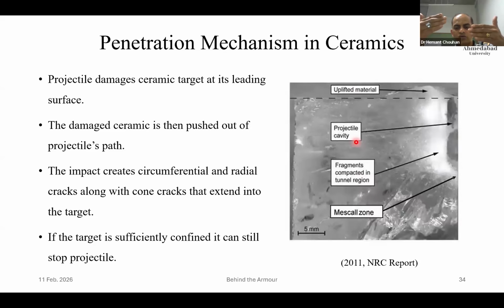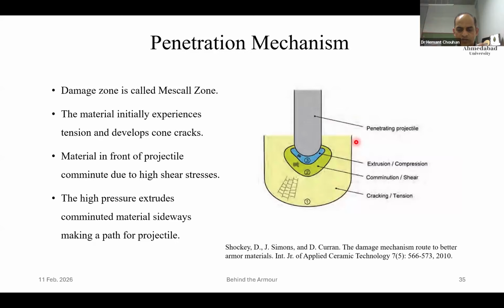If it is broken down and before that the tip has been eroded very well, so there is only a blunt part. Handling a blunt part is much easier than an ogive nosed high hardness material. So that way we are going to play with that material system here, both the parts, projectile as well as ceramic. So what happens? What is the mechanism behind? As your high hardness projectile will enter into the ceramic, a damage zone called the Mescall zone will be created. Initially, it will try to push the material.